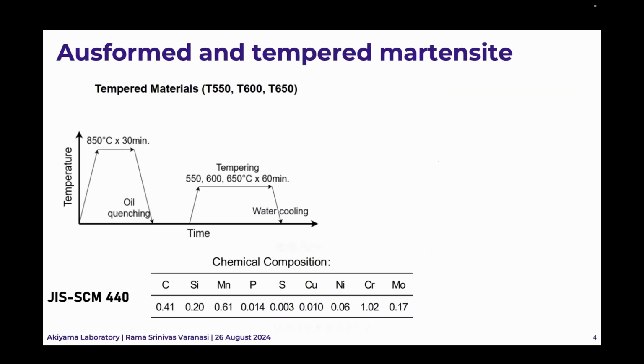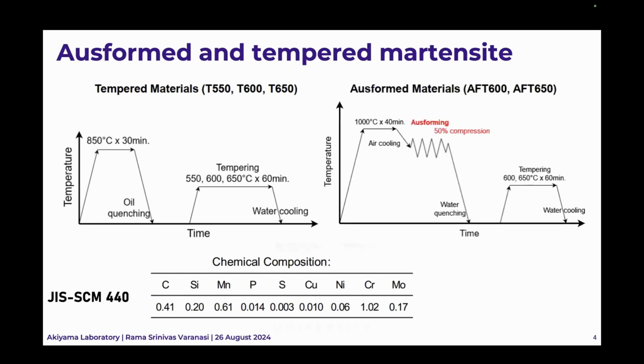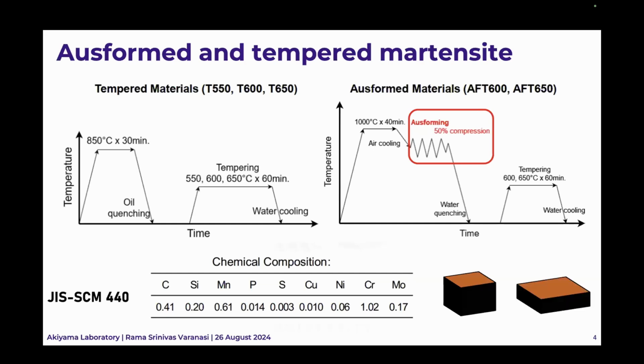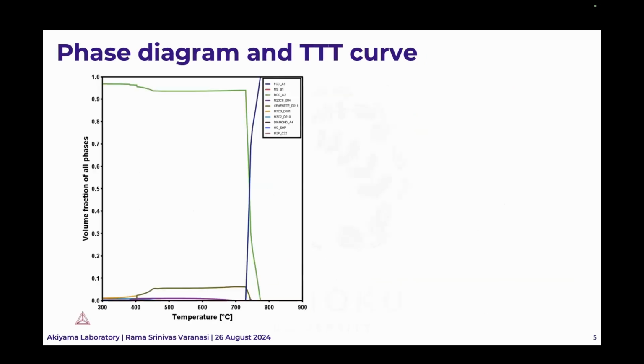So the previous steels were tempered materials, which will be referred to as T, and the ones with enhanced properties are Ausformed materials, where there is an Ausforming of about 50% compression, which is essentially like the sample has been taken out, and with a thermocouple, the surface temperature is measured, and then there is a 50% compression, and after that, again the typical tempering process.